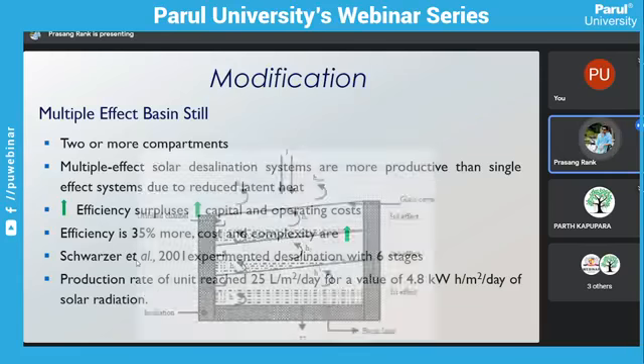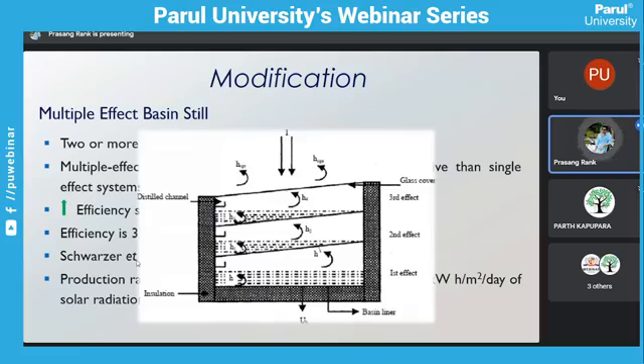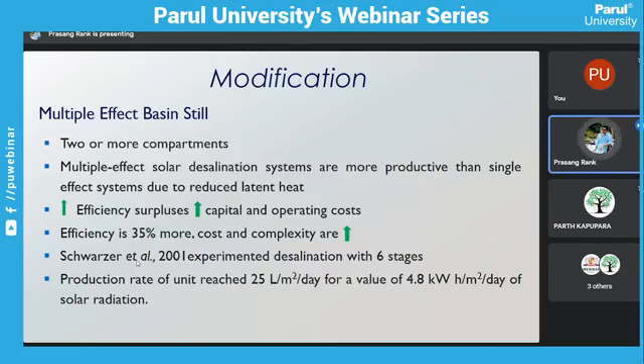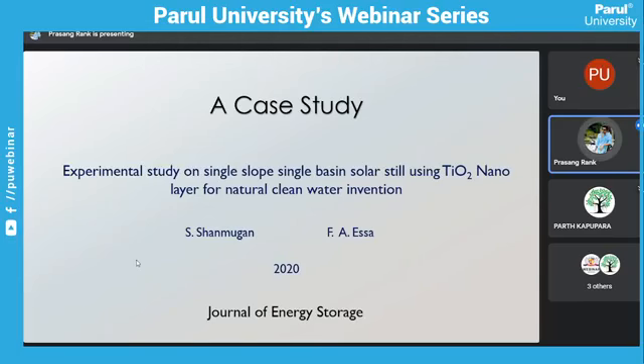Here we saw the photo of 3 stages. Same way, for 6 stages he studied desalination, and he found that production rate reached 25 liter per meter square per day for a value of around 4.8 kilowatt hour per meter square per day of solar radiation. So we can get much more water from multiple effect basin still compared to single effect basin. So in this way, we can modify it. So there is a small case study.